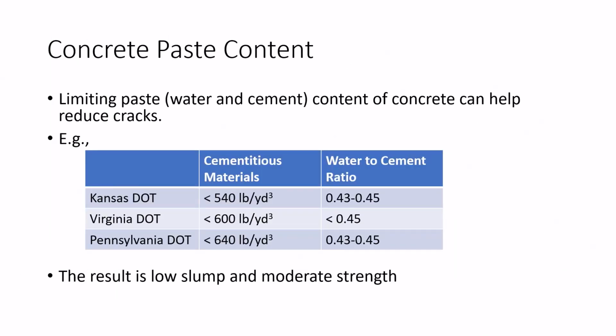So first thing that was discussed was what makes concrete mix crack less. It was discovered that for those modern mixes that have less cracks, the paste content was limited. If you limit that paste content, which would be our water and cement content, it does seem to result in fewer cracks, which does mean that it results in moderate strength, but the consensus was that we don't really need terribly high strength for concrete decks.